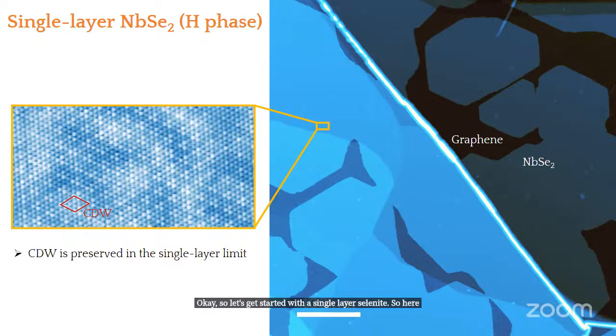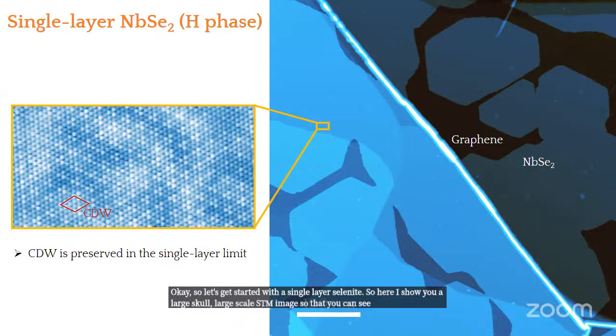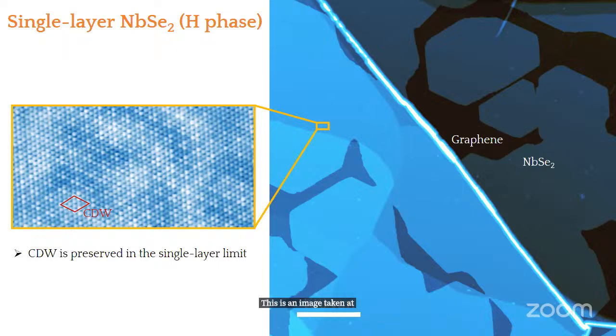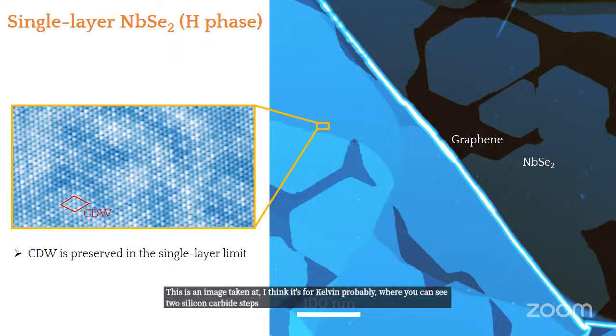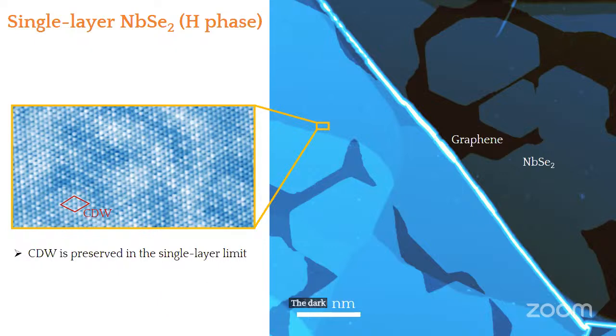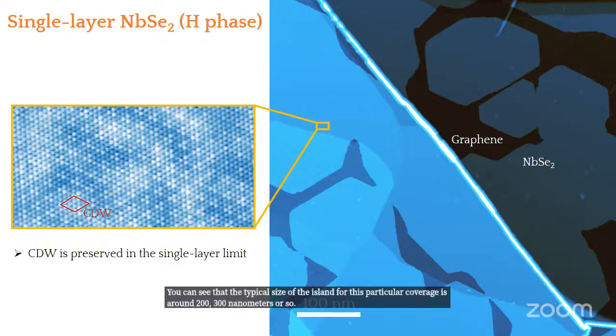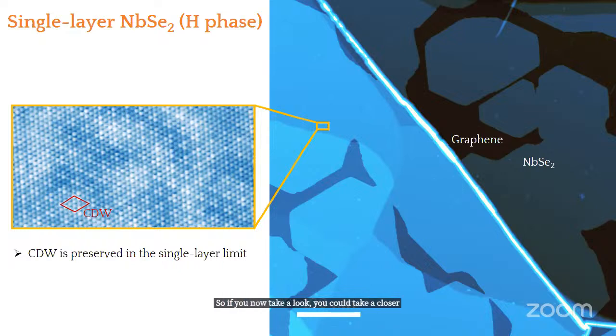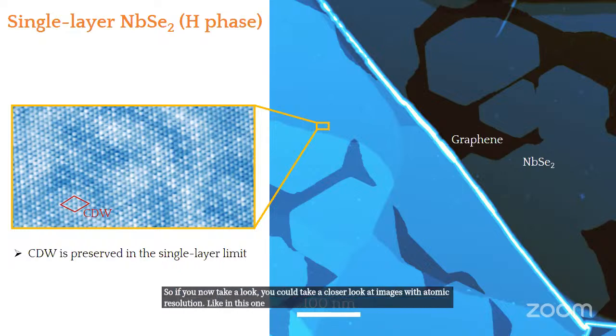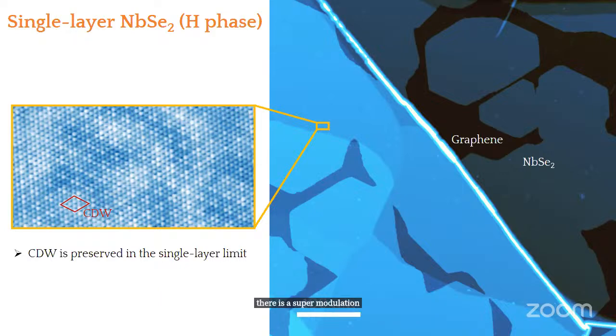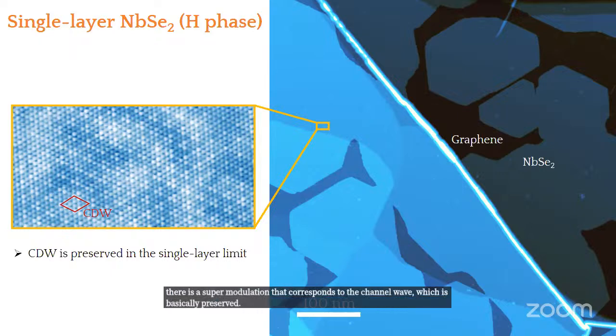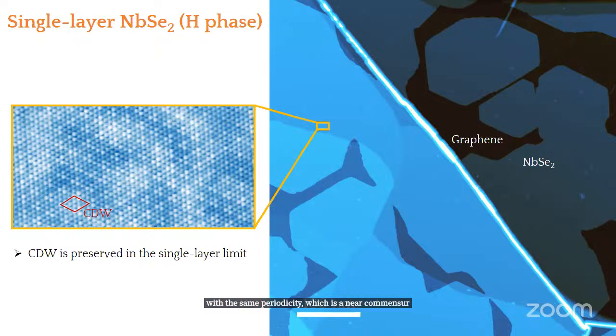So here I show you a large-scale STM image so that you can see the typical morphology of our samples. This is an image taken at, I think it's 4 Kelvin probably, where you can see two silicon carbide steps. Okay, so you look at this one, for example, the dark parts is the graphene, the substrate. Okay, and these islands are the islands of isolated niobium diselenide. So you can see that the typical size of the island for this particular coverage is around 200, 300 nanometers or so. So if you now take a closer look at images with atomic resolution, like in this one, you can see that apart from the atomic registry, there is a supermodulation that corresponds to the charge density wave, which is basically preserved with the same periodicity, which is a near commensurate 3x3 periodicity in niobium diselenide. It's preserved in the two-dimensional limit.